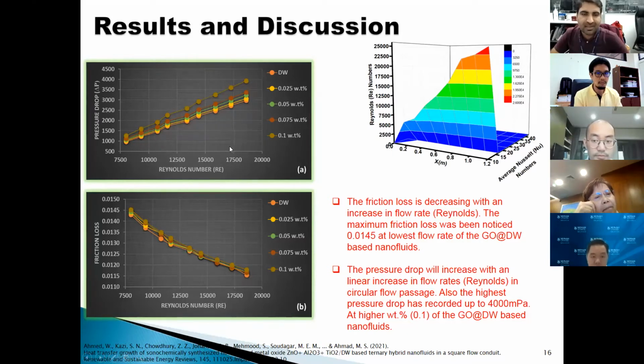And here you can see as the weight percent concentration is increasing, the pressure drop is increasing across the heat exchanger, across the test section. Why? When we add the nanoparticle in distilled water, it raises the viscosity of the distilled water. So as we are adding the nanoparticles, it is increasing the viscosity. And also with the increase in flow rate, the pressure drop is increasing.